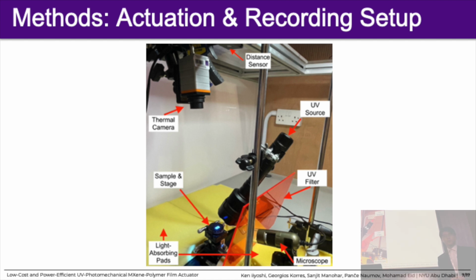So in terms of testing the actuation of the film, we have a simple setup consisting of first the film and, most importantly, the actuation source. The actuation source is a UV flashlight. It's a UV Beast, 365 nanometers. The radiation intensity is 5.4 milliwatts per square centimeter, so it's on the lower range, I would say. And then for the measurement, we used a thermal camera, a distance sensor, and a microscope with a UV filter so that we can show you guys cool videos.